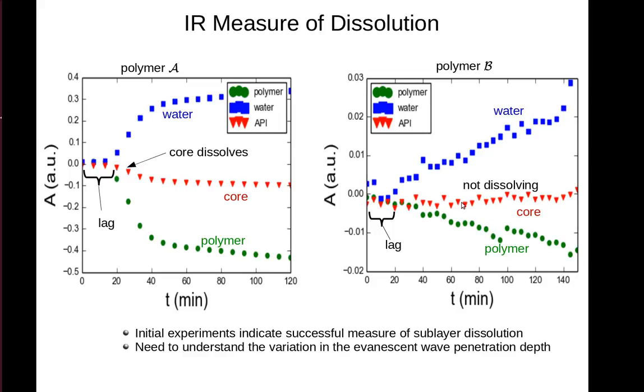Remember that Polymer B is relatively insoluble, so we don't expect that to go away as easily. And finally, we note that the core, the API, is not dissolving, suggesting that the insolubility of the polymer is trapping the API beneath the surface, keeping it in contact with that evanescent wave.